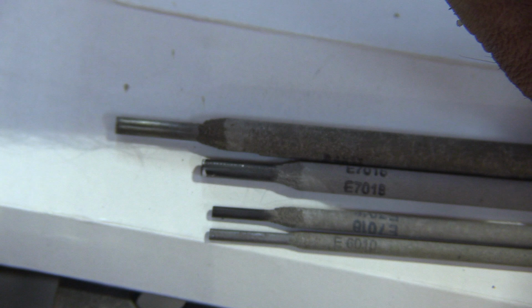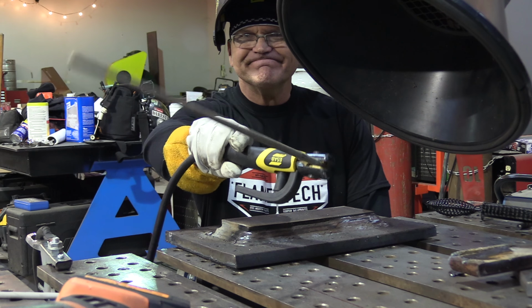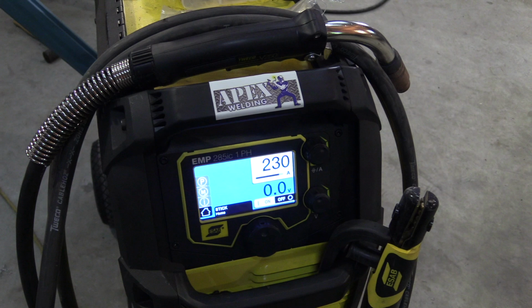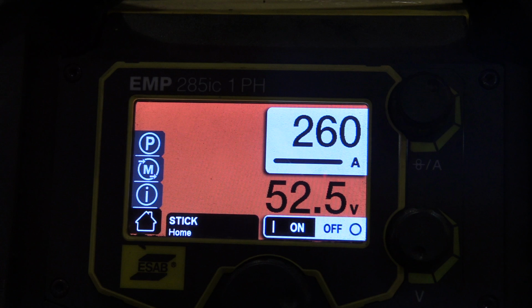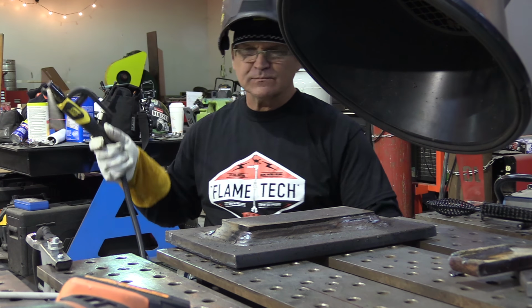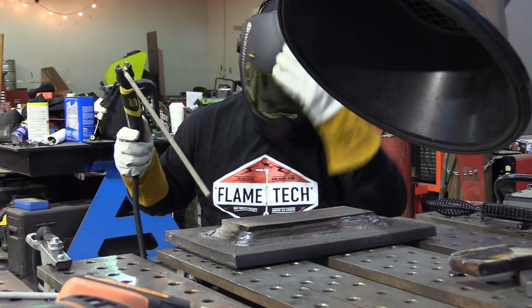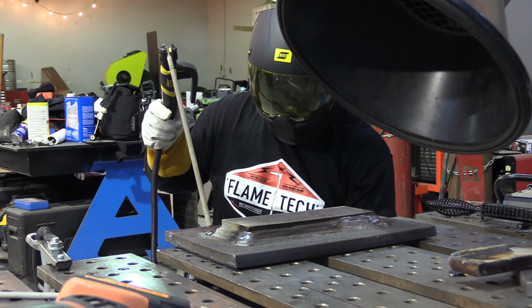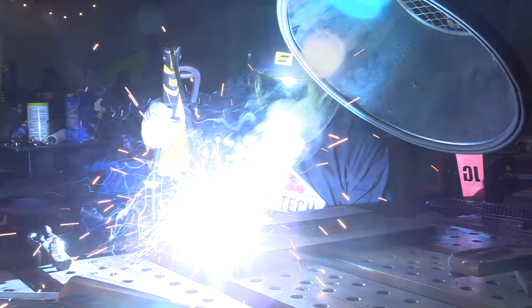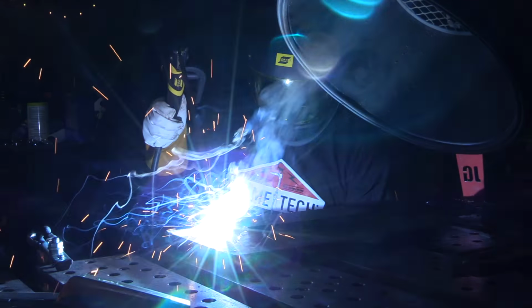That big rod on the top, even though the one under it is the same diameter, 3/16, it's much bigger due to all the extra iron powder in the flux. So previously we used 230 amps for the 7018. For the 7024, because of all that extra flux, extra iron powder, 260 amps is what we're going with here. 7024s are known as a drag rod, also kind of referred to as jet rod. That's a trade name of Lincoln's 7024. But they are used for large single pass welds primarily.